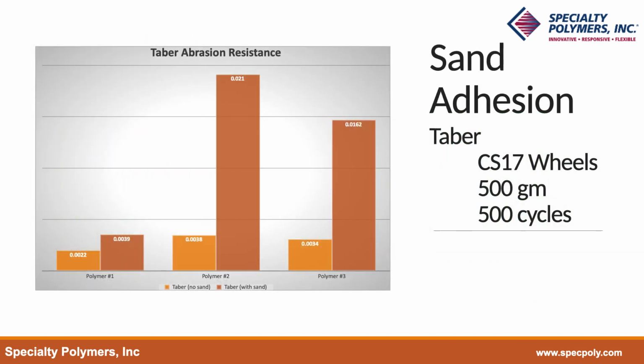We ran the Taber abrasion resistance with and without sand. It was interesting that there wasn't much difference without the sand, but in the testing with the sand, the darker orange bars, the crosslinking acrylic had much lower weight loss than the competitive acrylics. This may indicate that the sand retention of the crosslinked acrylic is better than the others.